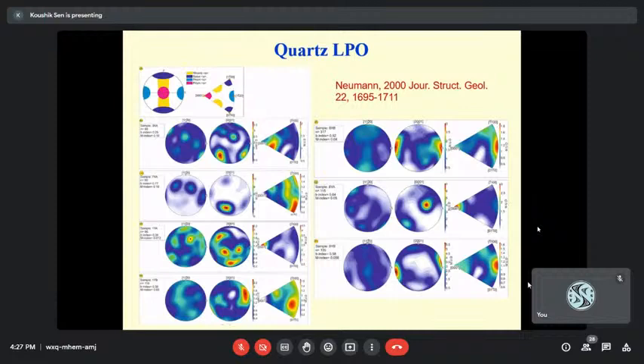depending on the degree of retrogression. Type 1 basically shows an L-type fabric, type 2 shows something like LS to SL type of fabric, and type 3 doesn't show any kind of fabric. And as far as the quartz is concerned, most of the samples show basal or prism A slip, and maybe sample 1YB also has a very strong component of prism C slip. So both high temperature as well as medium temperature slip systems can be inferred from the LPO of quartz.